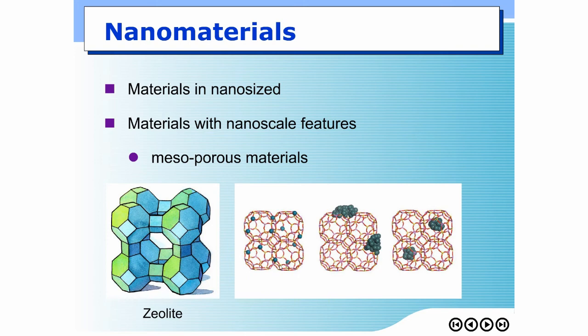On the other hand, if you put these metal catalysts inside this cage, like this picture inside the cage, the opening of this zeolite cage can screen the size of the reactant accessible to the catalyst inside. So you can use the structure of the zeolite to screen reactivity of your reactant.